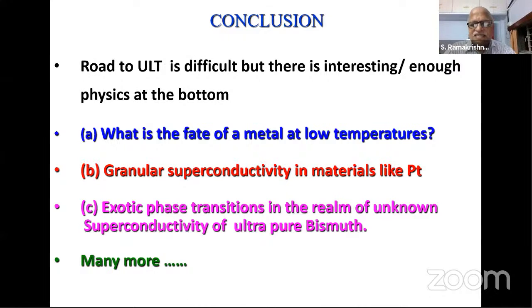Yeah, so there is no new force here. In the case of a BCS superconductor, as I explained, it is the lattice vibrations, which are called phonons, that are responsible for the binding of two electrons in the system. In bismuth, it is not very clear. One of the theories says that these holes change the dielectric nature of the bismuth. Bismuth has a very large dielectric constant, of the order of 100.